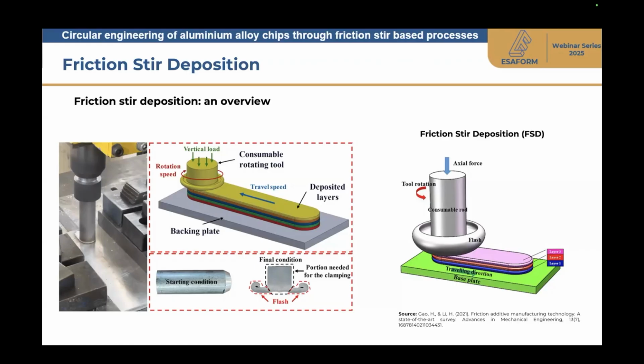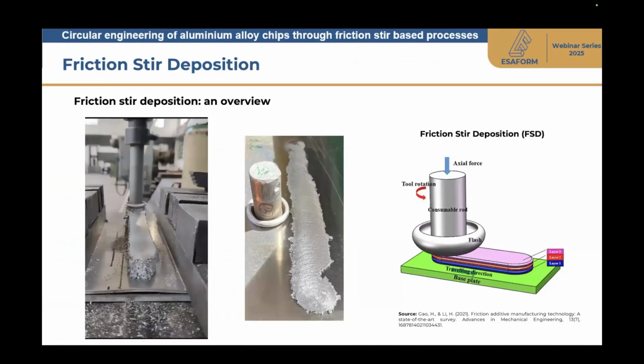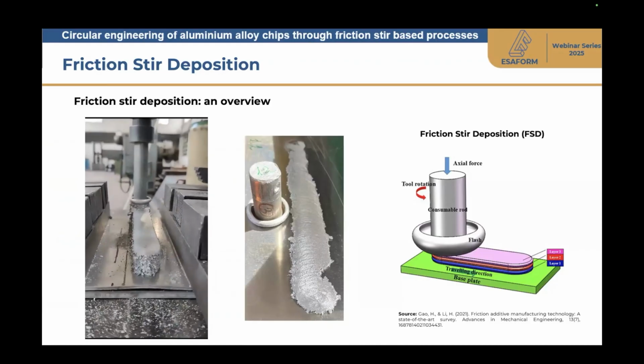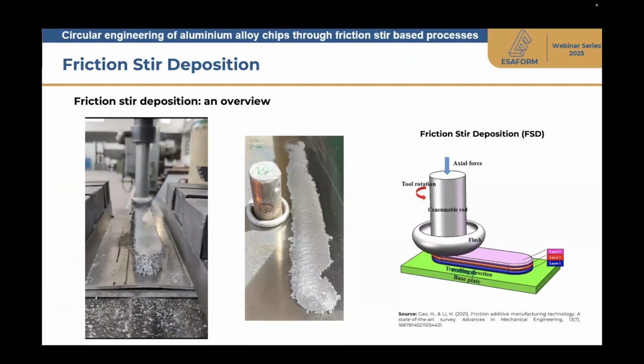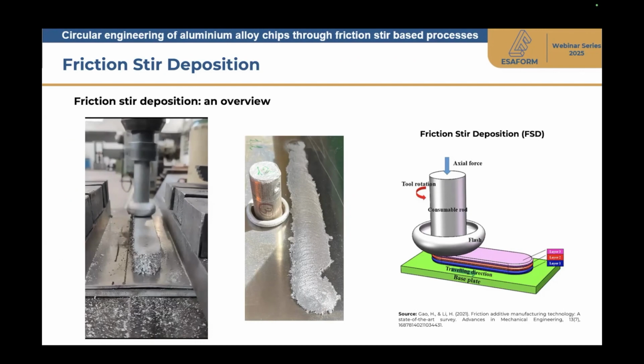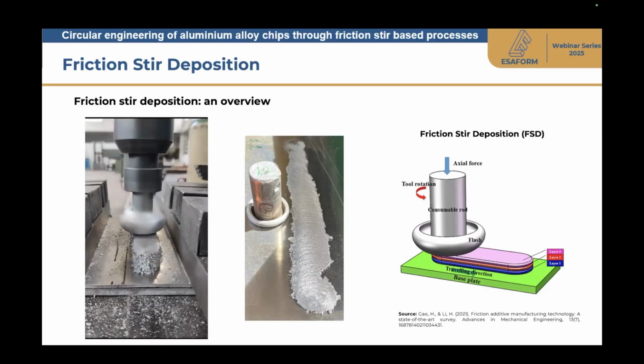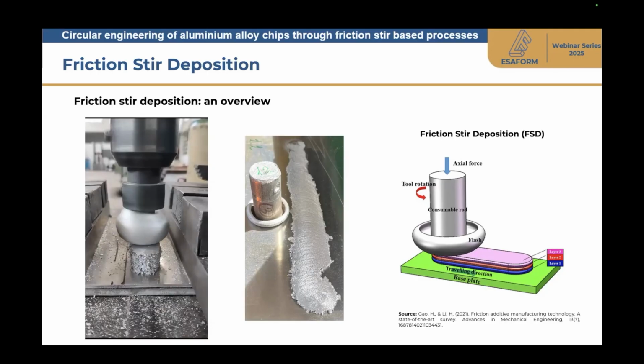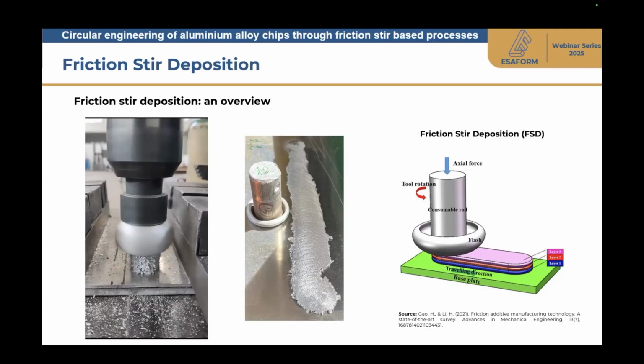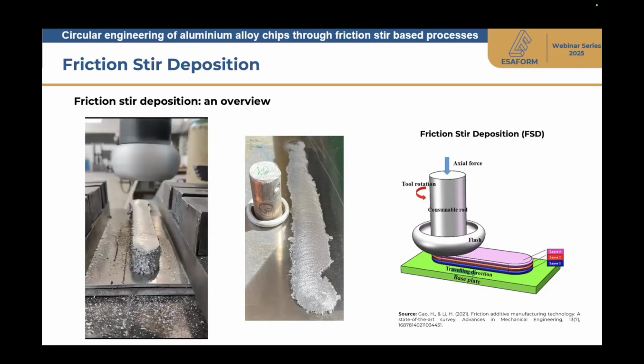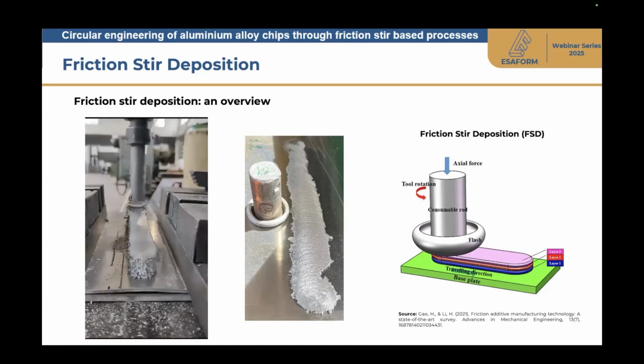Well, just to let you know or to understand what we're talking about, this is what happens during the process. And of course, considering a single layer, it is very difficult to control the actual deposition in terms of geometry of the deposited layer. And of course, at the end of the deposition, you sometimes have to machine, to mill the deposited wall in order to obtain a regular shape of the deposited material. But it is quite interesting and popular in the last years.